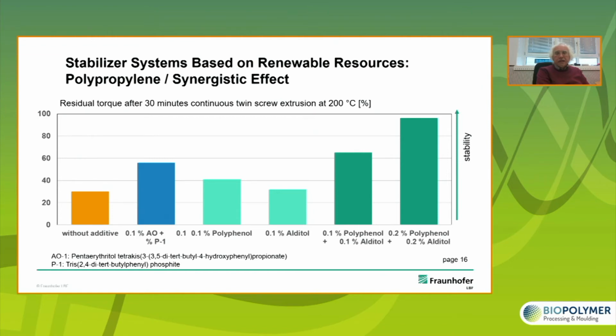That's to say, at the same concentration level, this combination of renewable resources material is as good as the classic combination AO plus P1. If I double the concentration, as you can see here on the far right side, then after 30 minutes testing time, I have hardly any loss at all.